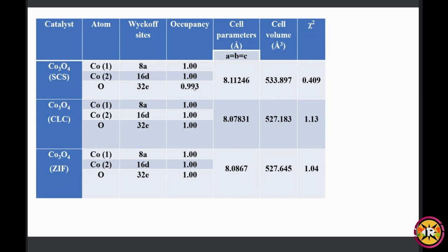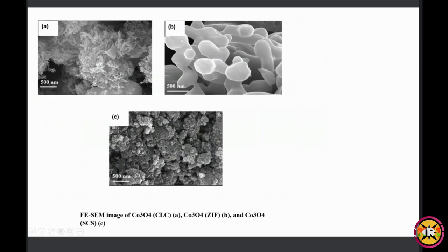So now coming to the FESEM, what I have observed here, for CLC, I saw a nanoflake kind of structure, and for ZIF it's quite interesting. When I calcined ZIF-67 at 450 degrees for 6 hours, the cubic shape of ZIF-67, as you can see, is still retained. But for Co3O4 SCS, as I have done calcination at high temperature for 10 hours, the morphology is just a chunk, kind of a nano chunk. So there is no such kind of morphology. But for ZIF-67, this morphology is still retained after calcination also.